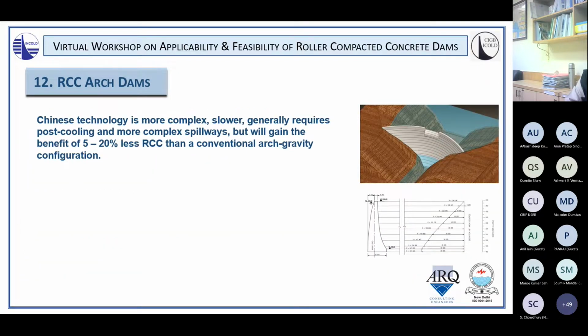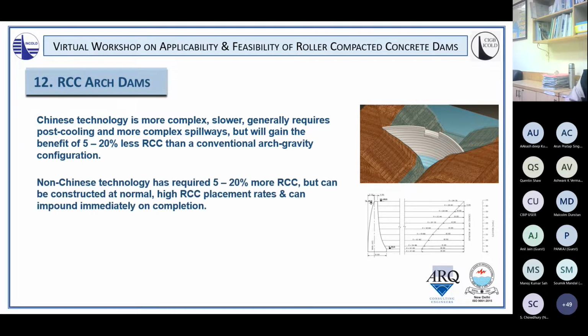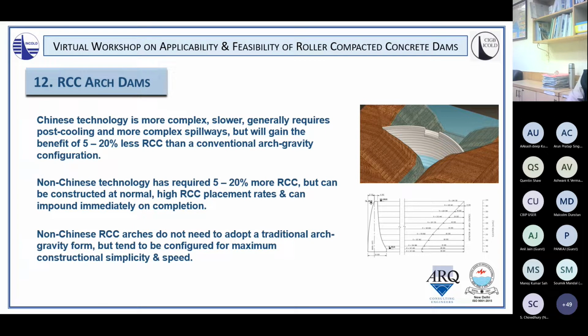So Chinese technology is more complex, slower, and generally requires post-cooling and more complex spillways, but will gain the benefit of between 5 and 20% less RCC than a conventional arch gravity RCC configuration. Non-Chinese technology has required, by the same token, between 5 and 20% more RCC, but can be constructed at normal high RCC placement rates and can impound immediately on completion without the need for post-cooling and grouting. Non-Chinese RCC arches do not need to adopt a traditional arch gravity form, but tend to be configured for maximum constructional simplicity and speed.